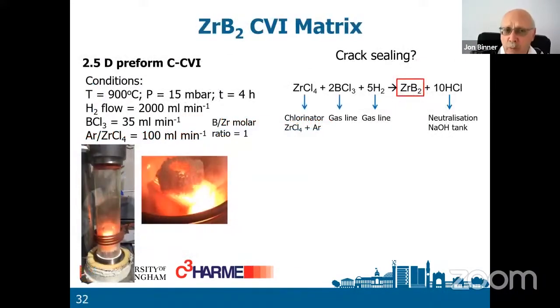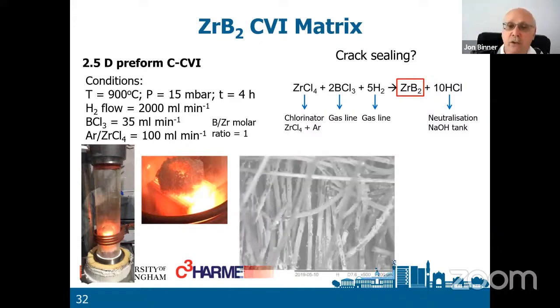We've also done some work on depositing not just a carbon matrix, but actually a zirconium diboride matrix. So we flow a mixture of boron chloride and zirconium chloride in an argon carrier gas through the system. You can see the RF system there. It's a simple tube with a coil around it, heats the sample up, deposits the material. There on the top right, you have got the equation, and the question is, does it work? And the answer is, yes, it does.